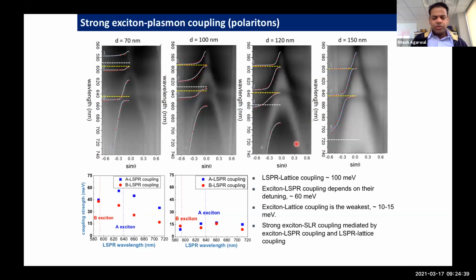Again, by improving the geometry. Instead of going with the bow ties, because bow ties can have very large inhomogeneous broadening, because these are triangles. So at the apexes, in the fabrication, you're going to have problems. Silver is a polycrystalline material, so you'll have rounding at the edges, and you can't control the rounding exactly over the large array. But if you have a nano disk, then it's sort of better.